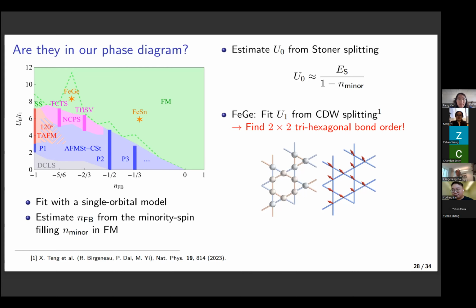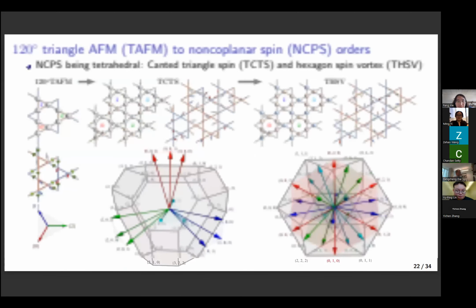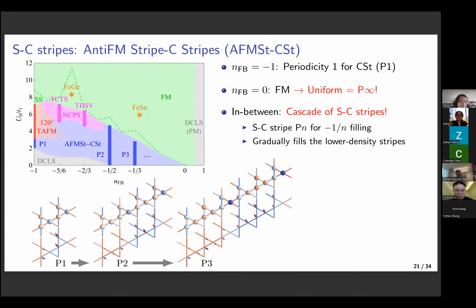I want to ask some detail about these stripe-like orders labeled by P1, P2, P3. So it seems that they are living in the background of this AFM as the charge ordered phase, right? So when you slightly dope the system from, for example, -1/3 to some other irrational values, how much energy difference would you observe in that process, and how would this difference change with the filling factor? Say you have 1/2, 1/3, 1/4. Is it getting smaller and smaller?